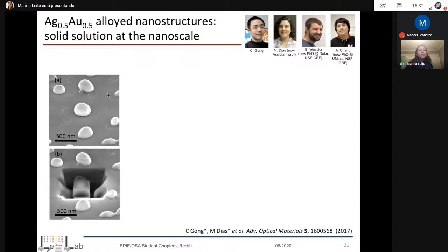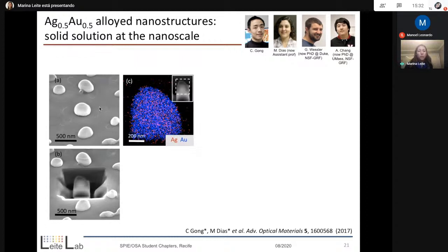So basically, if you look at a very representative nanoparticle, such as this one, I really like this image because you can even see the footprint of the film, right, of where the particles are and how the coalescence process takes place. This is really interesting. It's literally the footprint. It's not coincidence. So anyway, if you look into a representative nanoparticle, and we now map the chemical composition, in case you're wondering, hold on, do we really have a mixture, or is it a core-shell type of structure? Then we do energy dispersive X-ray spectroscopy, EDS or EDX, people call it both ways.